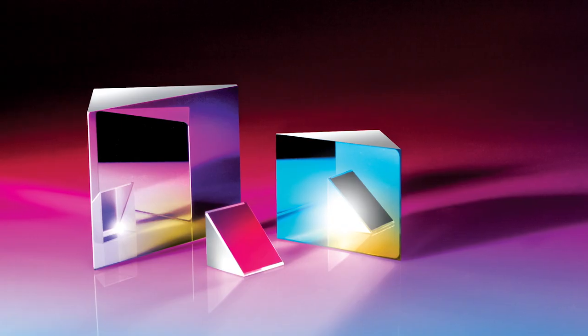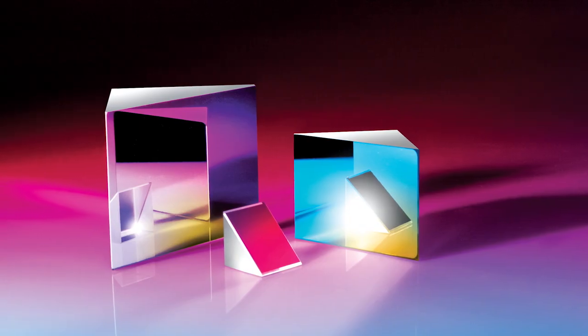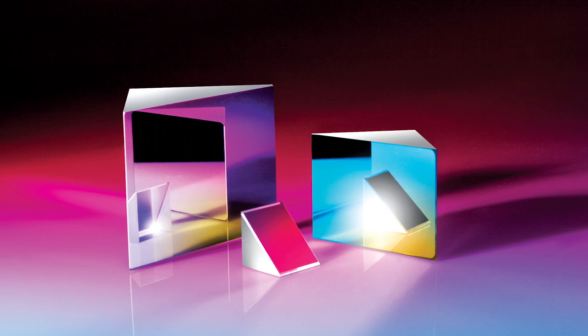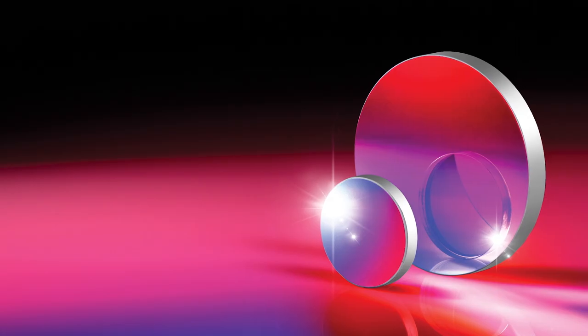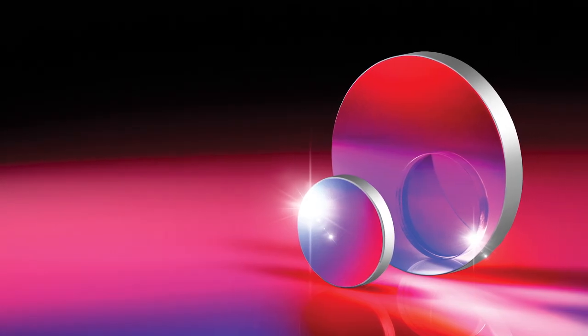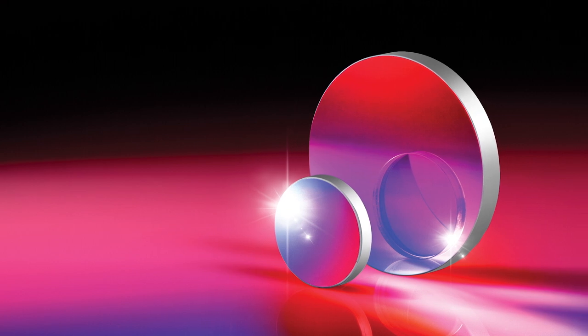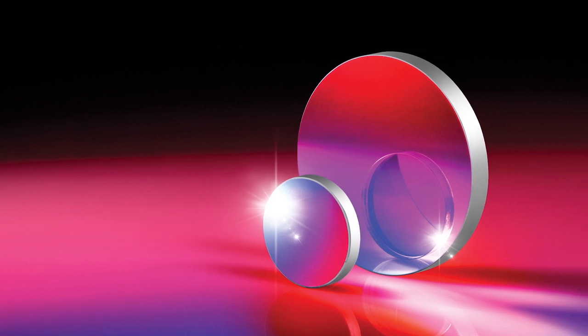On the other hand, highly reflective coatings are designed to maximize reflectance and are most often used on mirrors. The reflectivity is determined by the coating design, with the most important factor being the number of layers. All else being equal, the more layers, the higher the reflectivity, but also the longer the coating process and the higher the cost.